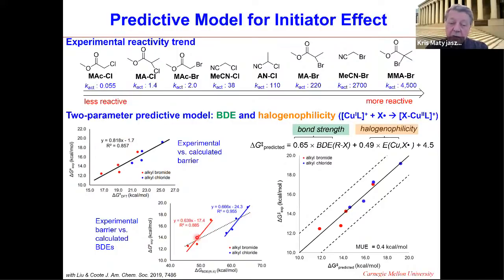Here is the dependence of the activation energy for bromides and for chlorides. You can see that the bond dissociation energy differs by approximately 10 kilocalories per mole, which means that bromides should be 1 million times more active than chlorides. In reality, they are maybe 10 or 20 times more active. The reason is halogenophilicity. As much as carbon prefers chlorine, so much more does copper prefer chlorine. So it is both the contribution of bond strength and halogenophilicity. As a result, bromides are more active than chlorides, but iodides, which have a very weak carbon-iodine bond, also have an extremely weak copper-iodine bond. In fact, copper(II) iodides are not known compounds. So here you have two parameters which are very important.